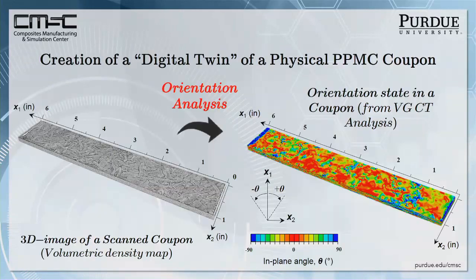And here is, let's take a part, let's scan it, let's find out where the orientation state is. This is a measure of orientation with angle with this x1 direction. And so the fibers that are red, this region of red, they're mostly pointed in this direction, or they're blue, they're mostly 90 degrees to that direction in that area. And by the way, that affects the strength property and the behavioral characteristics. You cannot assume this material is homogeneous. It isn't, even at a scale that's of interest to us. Well, all materials aren't homogeneous at some scale, but this is a mesoscale that's reasonable.